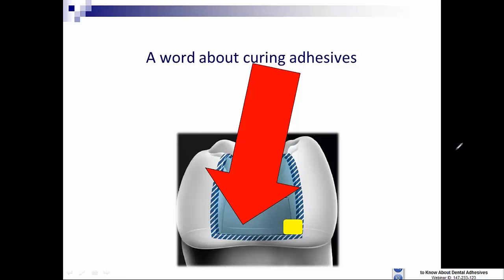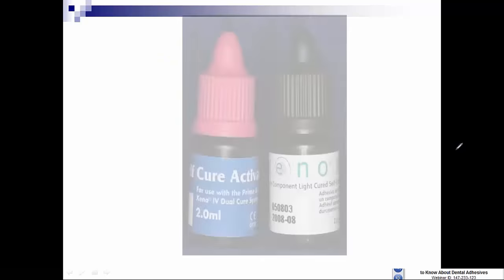Thus, our recommendation is that in a cavity preparation like this, you cure for 10 seconds from at least two angles when you have a significant number of vertical cavity walls to be sure that the photopolymerization energy is as much perpendicular to all the surfaces as possible.